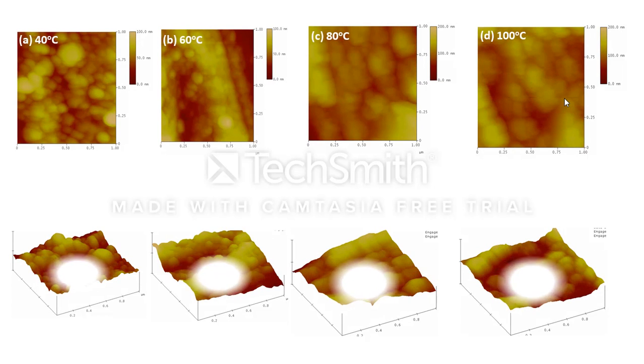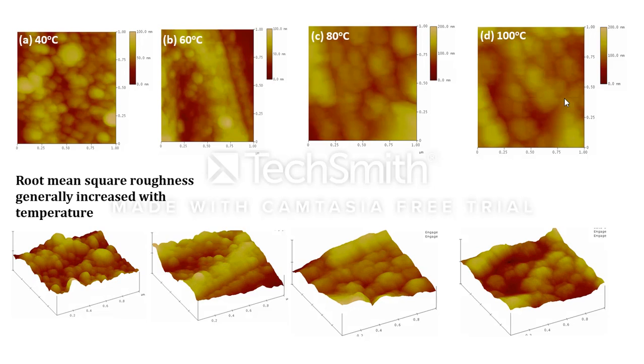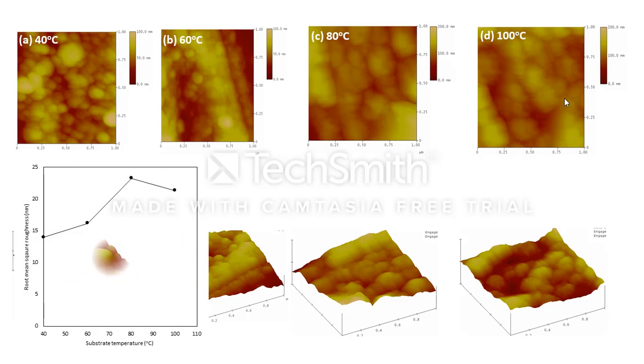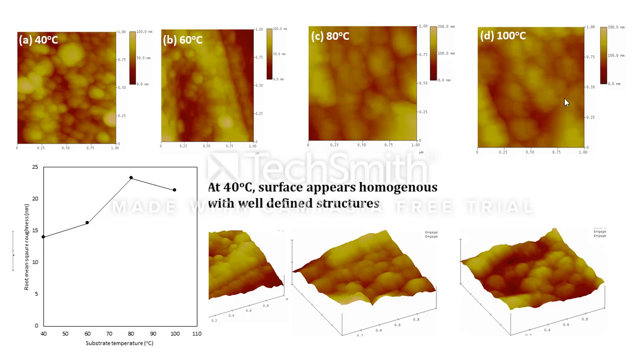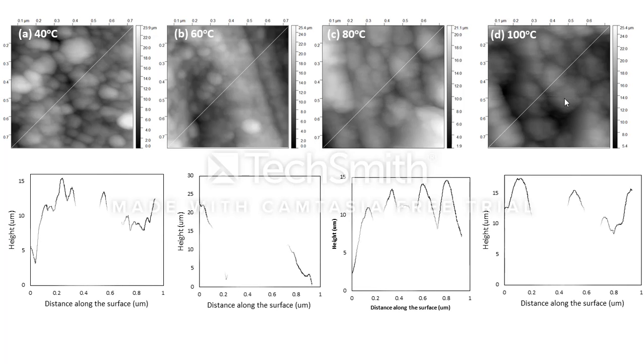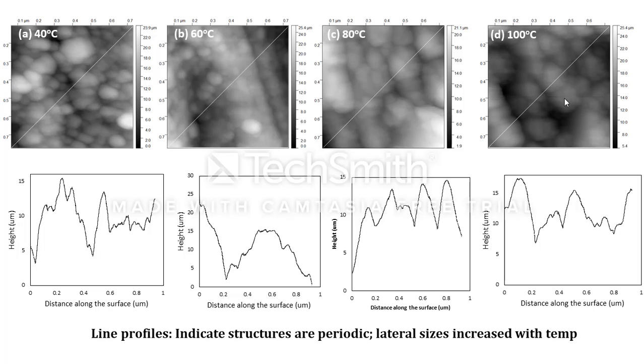The AFM results show that the root mean square increases with temperature, and a plot of that is illustrated. And at higher temperature there is aggregation of structures and hence higher surface roughness. Then we did the section profiling, and the structures were shown to exhibit periodic structure, and the lateral sizes shown to increase with temperature.